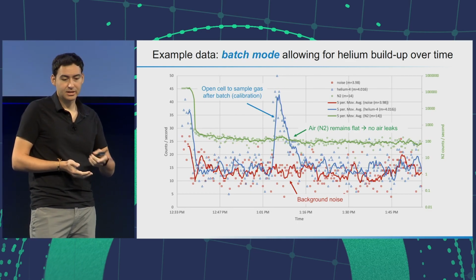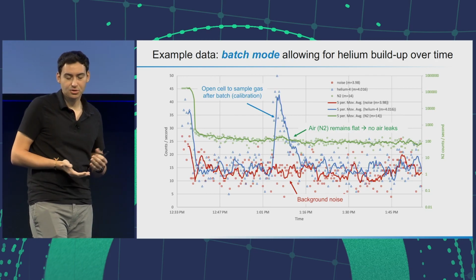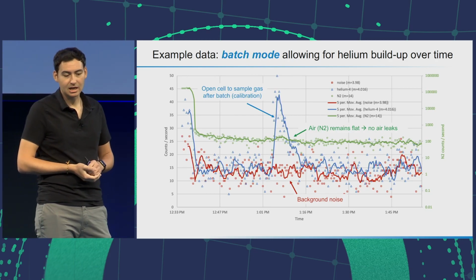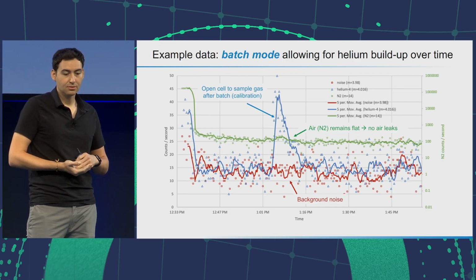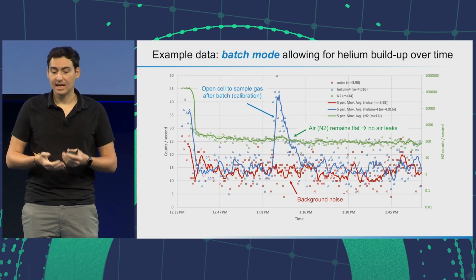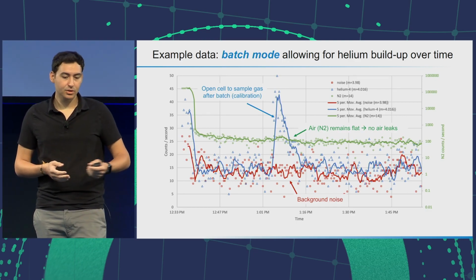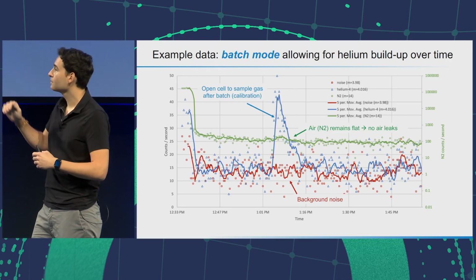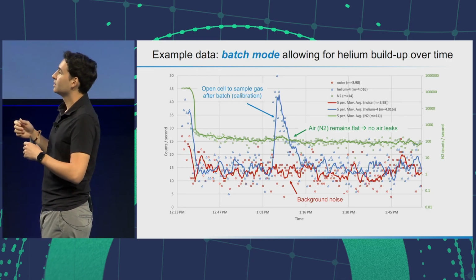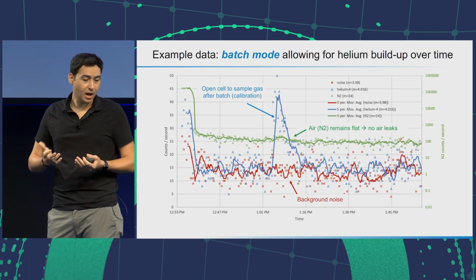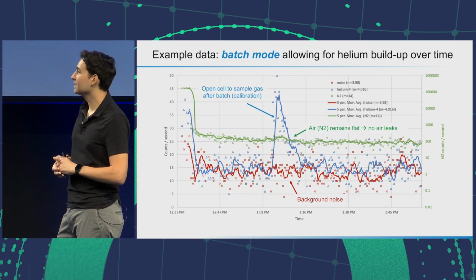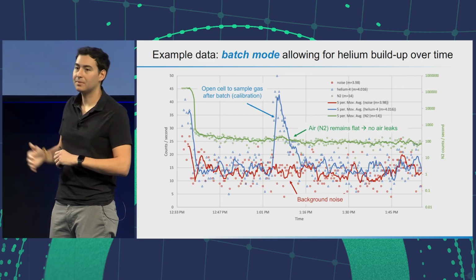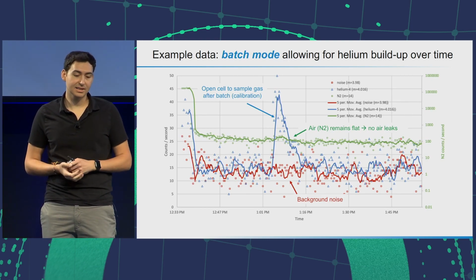The green plotted on the right-hand side, that's nitrogen, so measuring air contamination on a log scale. And the blue and red correspond to helium and the background noise for helium. And so we start the flow, and you can see it levels off. And then we open up the cell that was closed before. We unbatch it, and we see a clear bump in helium, which decays back to the background level as the cell is purged with gases.